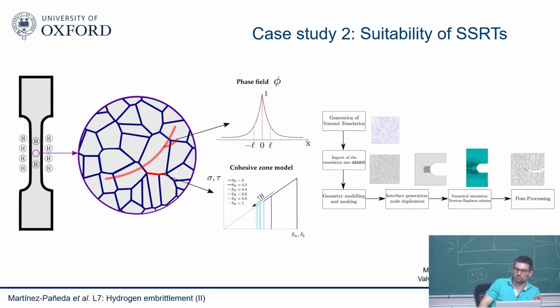And because we're looking into this problem and another problem that was also quite interesting, what if we took a different approach to this? We assume that the phase field tells me whether I have ductile damage. The phase field is going to model ductile fracture only. And then I resolve my microstructure. I do Voronoi tessellation and I put grains in there. And then I put cohesive elements in those grain boundaries.